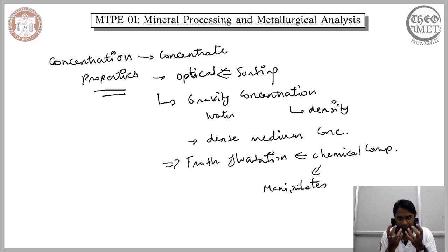So even though the froth flotation involves a chemical reagent, even though it involves a chemical reaction, it is largely confined to the surface, and even the manipulation of the surface is not a change in the chemical composition, but it changes the way a particle would behave in water. So essentially, the chemical reagent employed in the froth flotation interacts with the different particles, and depending on the chemical composition of the particle, the interaction would vary, and some interaction would give a specific way in which the particle would relate to water.